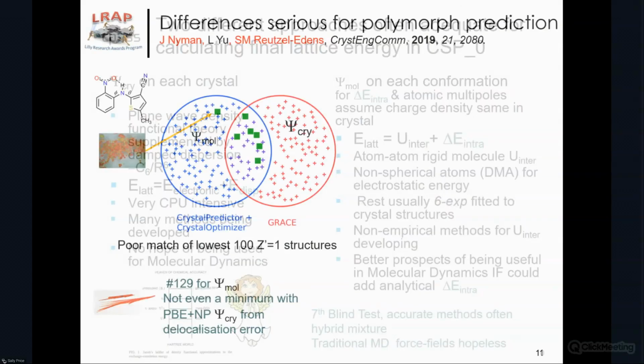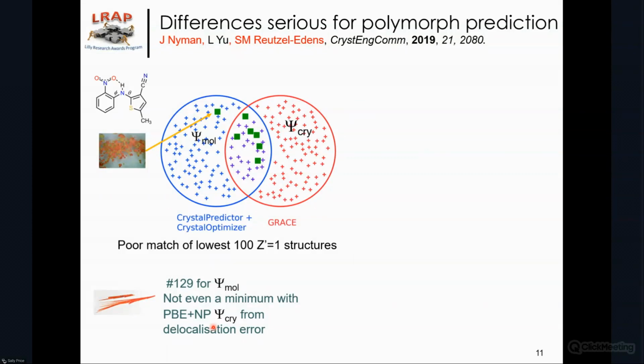And the differences between the approaches are important. Eli Lilly were in the good position where they could compare for ROY the published search I showed earlier with one done by the company's Schrödinger simulations software, and just look at the overlap of the lowest 100 one molecule in the asymmetric unit crystal structures. Okay, the overlap contains many of the polymorphs, doesn't contain one of them, and neither of them contain one of the known polymorphs. In our case, it was 29 above the top 100, and it isn't even a minimum with the periodic PBE dispersion correction calculations, from the delocalization error.